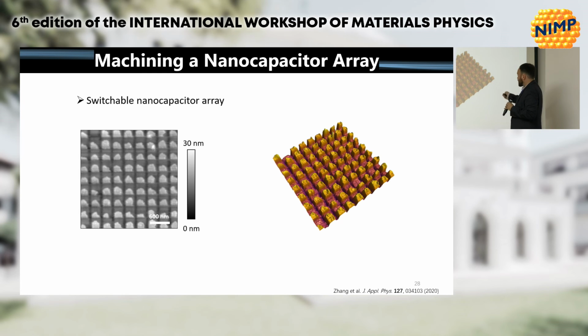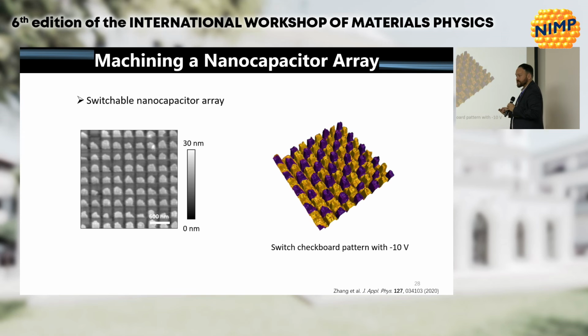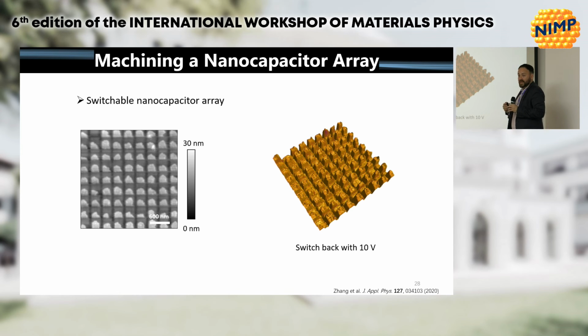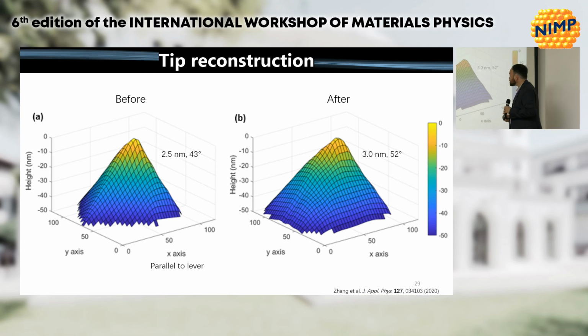Here's a 3D representation of the phase map. We switch it into a checkerboard structure and switch it back. So fortunately, it does retain the ferroelectricity. I think there's some promising avenues here where we can carve structures and we can carve electrodes. We can do it in the same system. So we can, in principle, make some more exotic structures that would be very challenging for labs without focused ion beam to do, and maybe without the need to deal with the ion implantation.